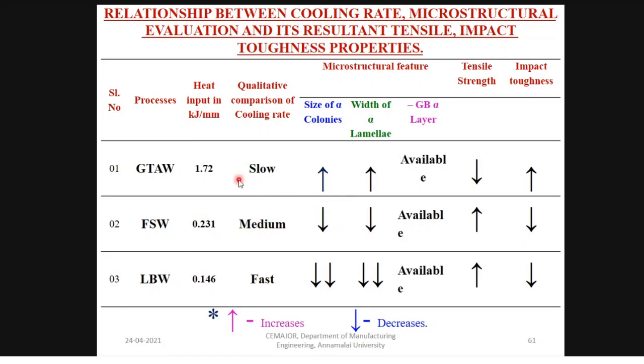Because of this cooling rate difference, the alpha colonies and the width of the colonies change. Tensile strength decreases because of the slow cooling, and the alpha colony size is wider, bigger, so it is low strength, but toughness is higher. But in the LBW, it's a fast cooling, so the alpha colony size is smaller, the tensile strength is higher, but the toughness is low. But in the FSW, it is medium. Though it is medium, there's a small decrease in the impact toughness.